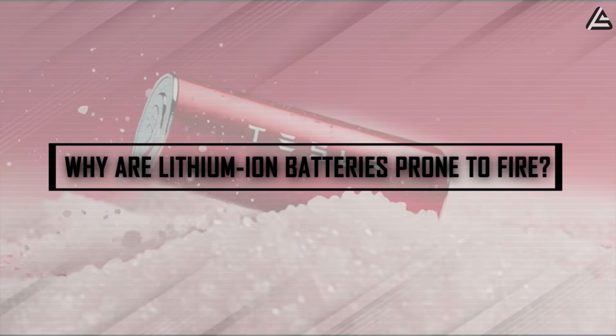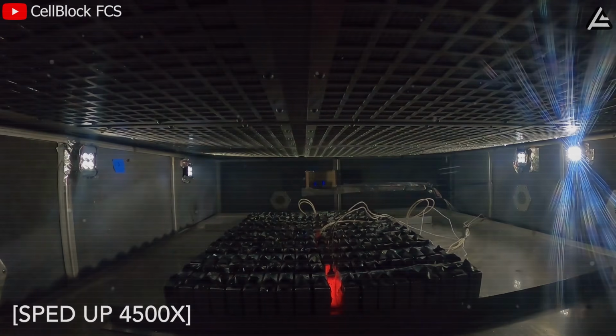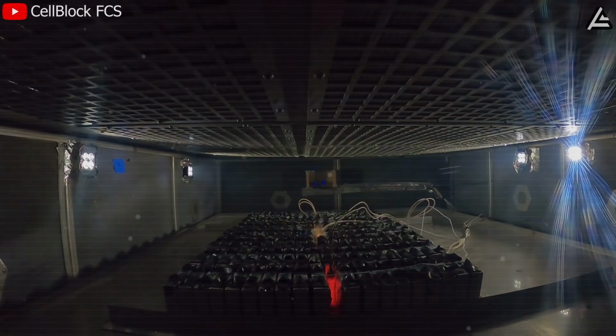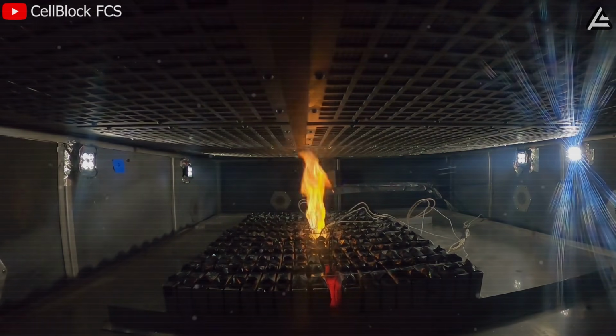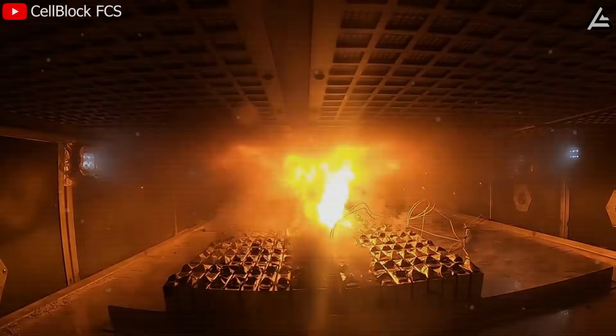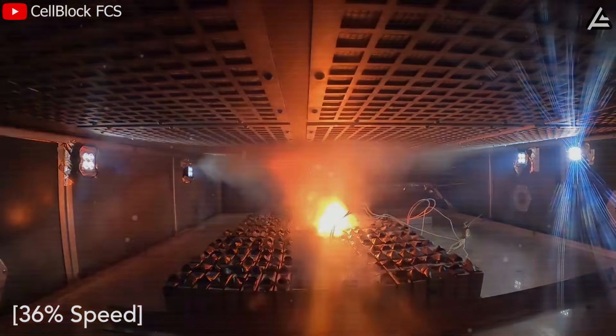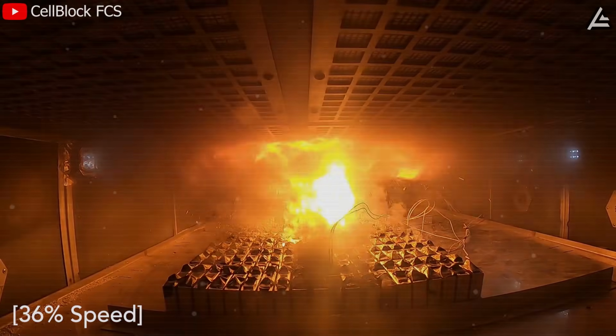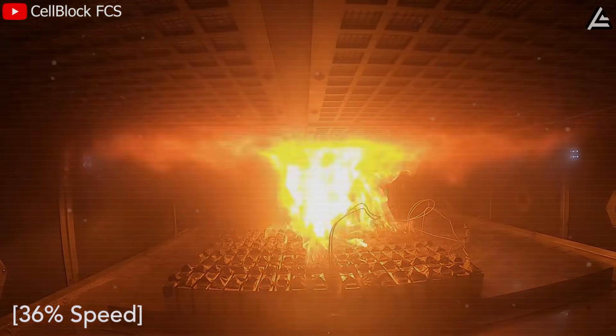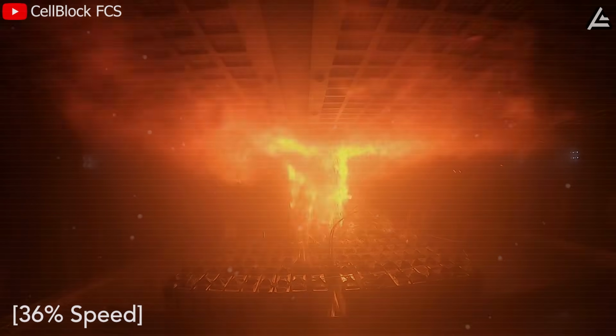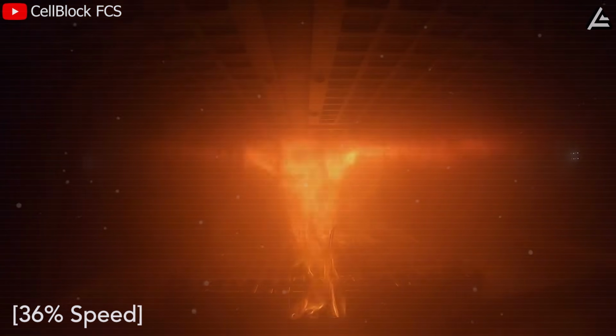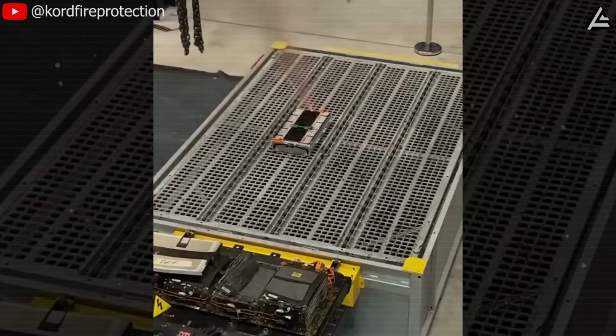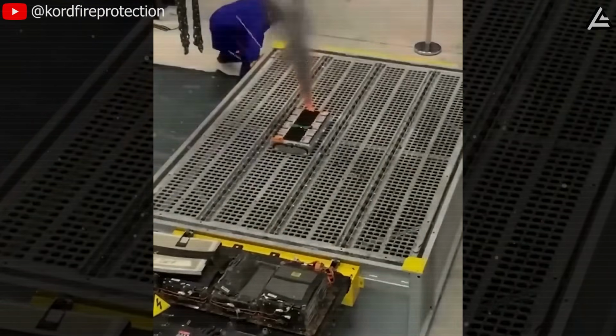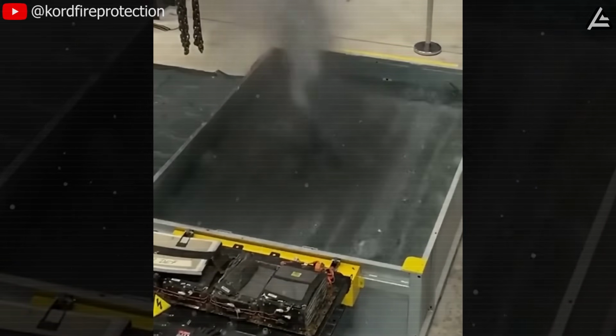Why are lithium-ion batteries prone to fire? The fire risk tied to today's EVs comes down to one well-known weakness: lithium-ion chemistry. When a cell is punctured, overcharged, or exposed to sustained heat, the internal reaction can accelerate uncontrollably, a chain event known as thermal runaway. Temperatures inside the cell can climb from a stable 40 to 50 degrees Celsius operating range to well over 500 degrees Celsius in under a minute, hot enough to ignite the flammable electrolyte and spread flames across neighboring cells. Unlike sodium or other less reactive elements, lithium reacts violently with moisture and oxygen, amplifying the danger once a casing is breached.